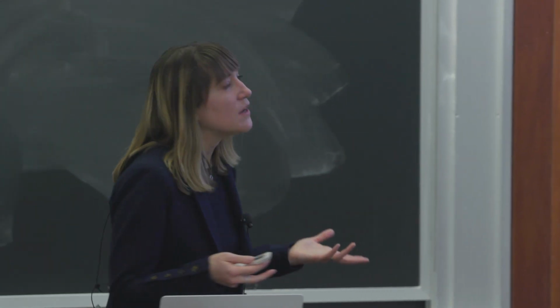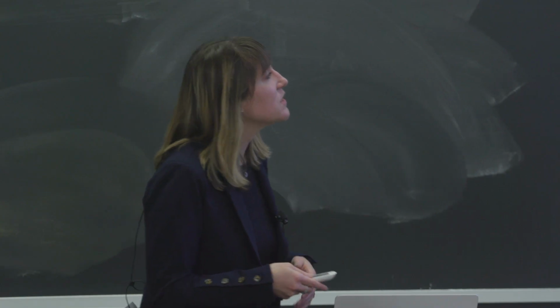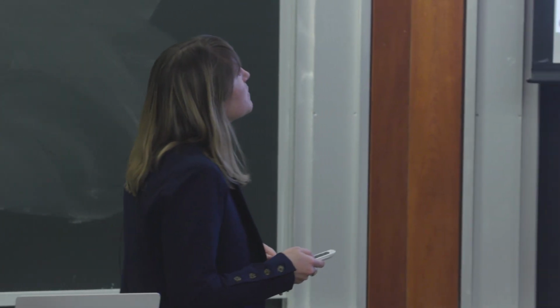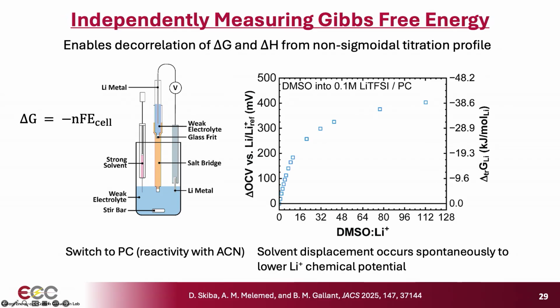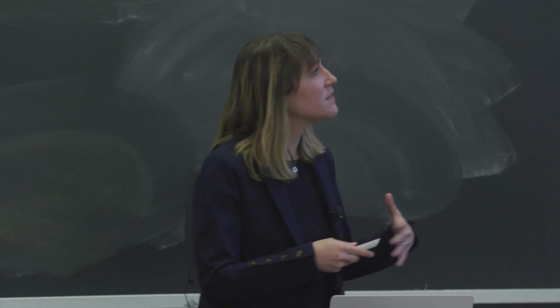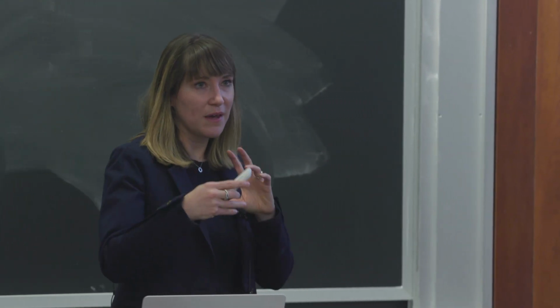So we need an independent measure that can help us bring more information into the analysis. And so we can exploit the fact that by the Gibbs-Faraday relation shown here, the Gibbs free energy change in an electrochemical cell is directly proportional to the open circuit voltage of the cell. So we can do in an electrochemical cell the same titration experiment and monitor, as we titrate the strongly coordinating solvent in, how the open circuit voltage responds, and that's reflecting the stabilization of lithium as it's increasingly coordinated by DMSO. So we get nice data sets as shown here.